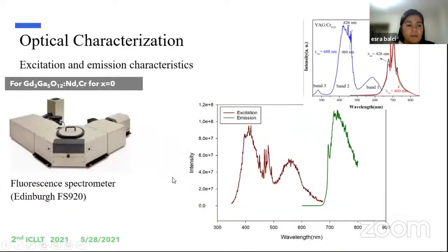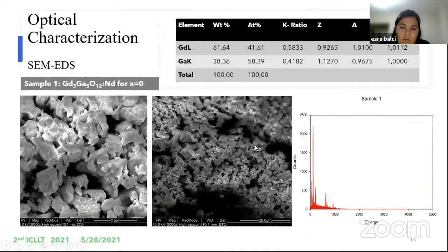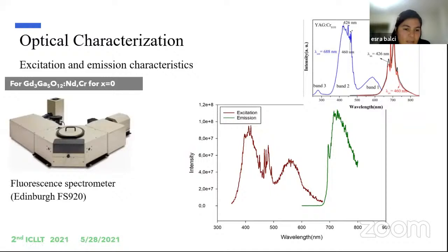Now we came to the second spectrometer, the fluorescence spectrometer. As you can see, there are 2 graphs, and the emission wavelength peak is around 725 nanometers, and the excitation wavelength peak is around 430 nanometers. And the emission of the phosphor must also lie in the optical window, and the excitation of the phosphor